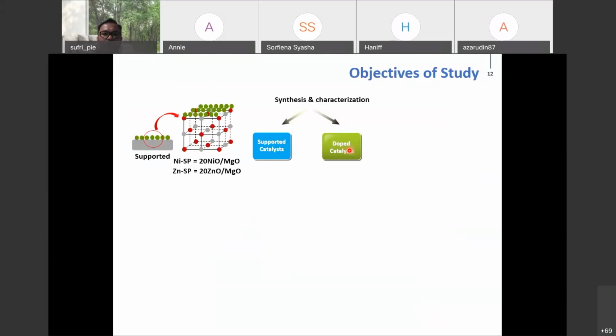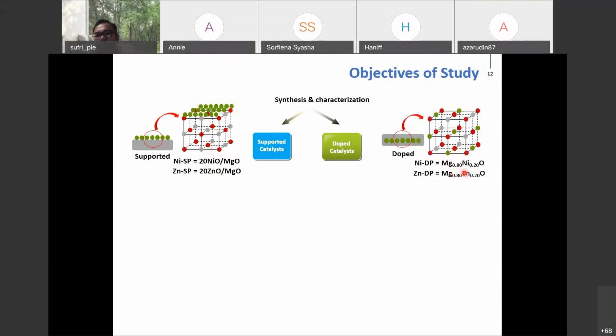For the objective of the study, I synthesized and characterized two classes of catalysts: supported catalyst and doped catalyst. For the supported catalyst, the active metals, nickel oxide and zinc oxide, will be supported onto the magnesium oxide, which is the catalyst support. For the doped catalyst, the active metals nickel and zinc will be substituted, or doped substitutionally, inserted into the cubic structure of the magnesium oxide. I think from this diagram, you can differentiate the supported catalyst from the doped catalyst.